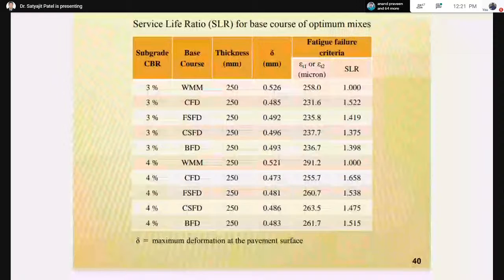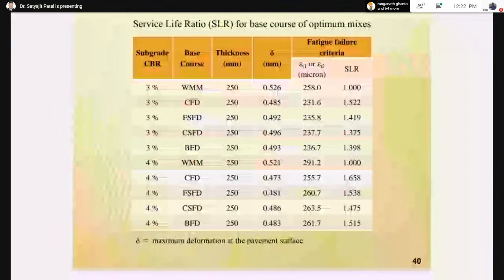So if you see here, the tensile strength obtained at the bottom of the bituminous layer has been observed from the Plaxis analysis, and accordingly the service life ratio has been obtained. So the service life ratio of 1.522 indicates that if your control pavement or conventional pavement is designed for 10 years, then this CFD material will last for over 15.2 years. That means its service life is 1.5 times that of conventional material. So the service life of any material you can determine with the help of this numerical analysis.